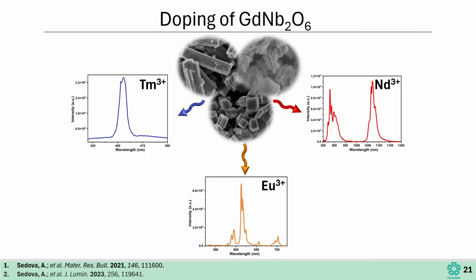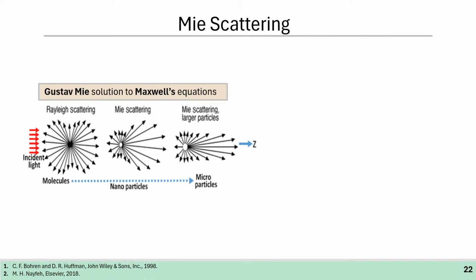So why do we even need all these morphologies and all these sizes of the materials? If we talk about optical emission, the size matters. The smaller the particles, and more precisely the crystalline size, the more efficient the optical emission will be. For example, here the flowers are medium-sized particles, but they have the smallest crystalline size, and they showed the most efficient optical emission. Where else can the size matter? In Mie scattering. So briefly about Mie scattering.